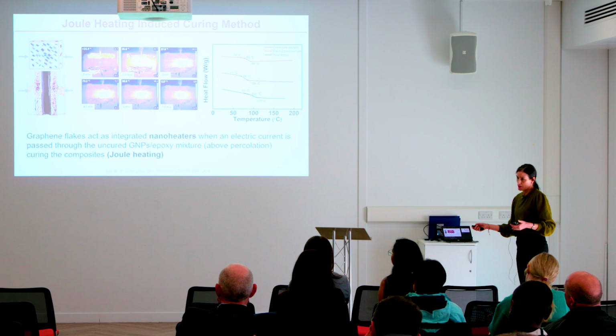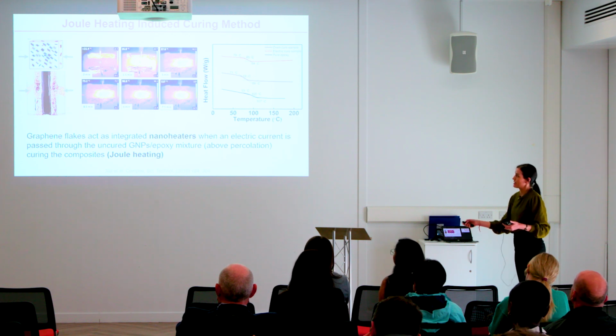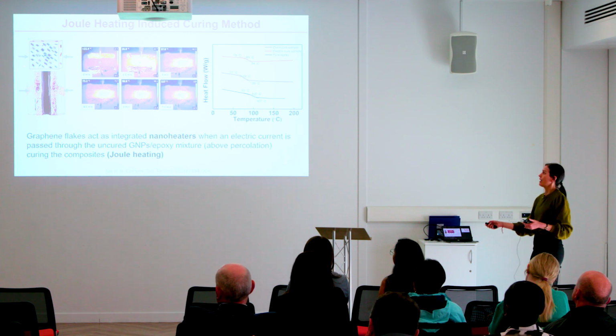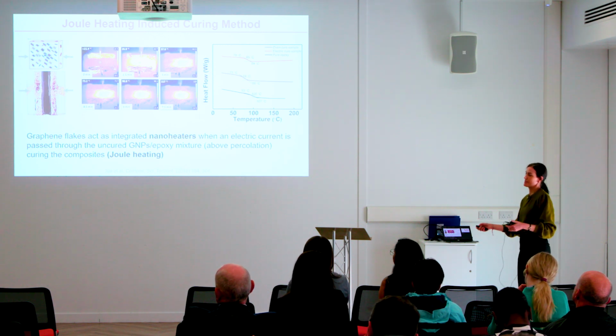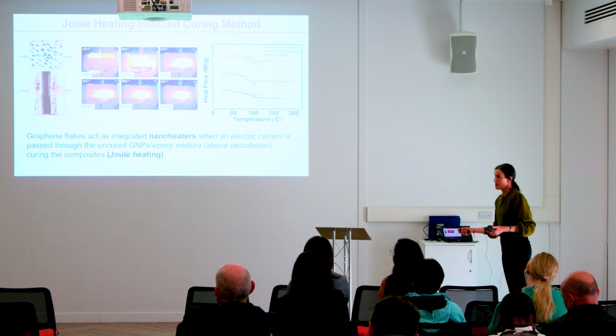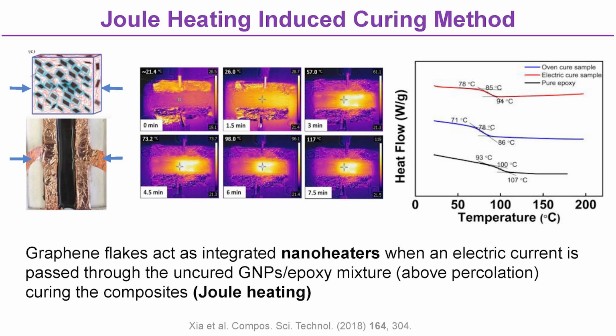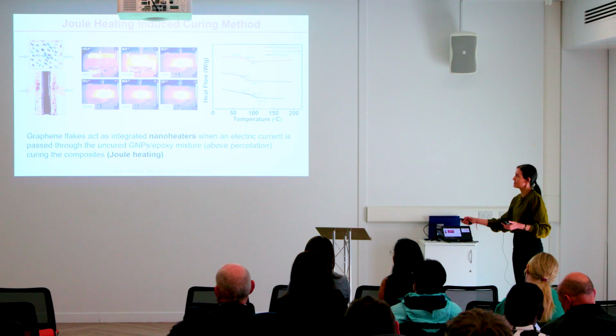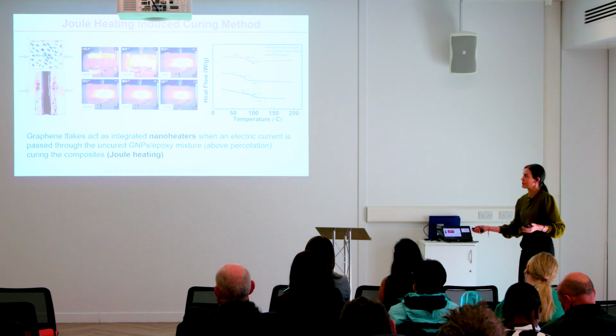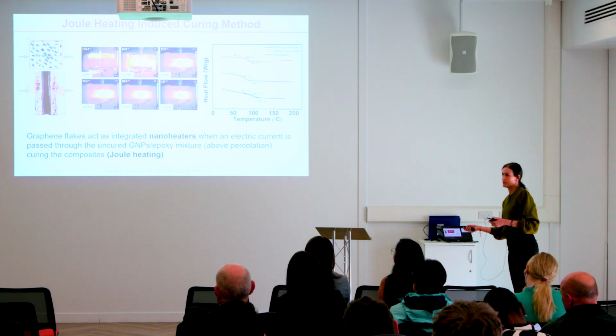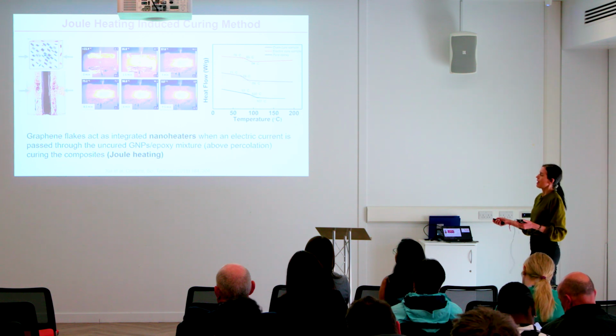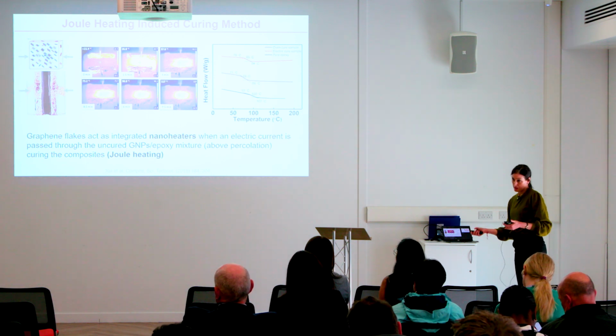So once we are above the percolation threshold, we found that when we apply an electric current through this uncured system, this electrically conductive network of graphene incorporated into the polymer could effectively transform the electric current into heat, generating heat from inside through a very simple Joule heating effect, and successfully curing completely the nanocomposite. We could control this generated Joule heat very easily using an IR camera, as we can see here. And we found that by controlling the applied voltage, we could actually control the heating rate, the achieved temperature, and we could also maintain the desired temperature for a particular number of hours, depending on the required conditions to completely cure a particular epoxy system.